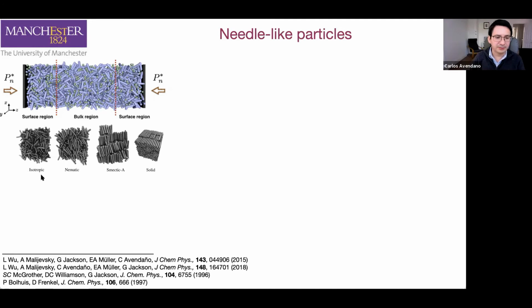Typically, when you have a pure component system, for example, these cylinders, you can run a simulation where you have your particles in a box, and then you can run a simulation in the NPT ensemble. You keep increasing the density of the system and observe the transformation of the system. When we have binary mixtures, we know that we cannot do that. Think of the typical phase diagram of a binary mixture that we tend to study in chemical engineering, something like hexane or a mixture of alkanes. You know that as soon as you enter into the phase coexistence region, the system will split into two phases, each of them with different compositions. Therefore, we cannot use the same technique as for pure components. We cannot just simply put a mixture with a given concentration and increase the density. We have to allow the system to separate into phases with different compositions.